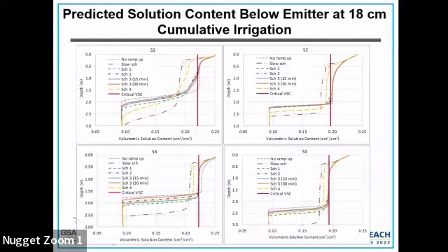And after about 7 inches, the one we show was just one ore, this is S1 and S2. And then you can see only the red one is the slow scheme, and the yellow one is scheme 4. And both schemes survived from the collapse. While the other schemes actually start experiencing the major collapse. And this is for all four cases.